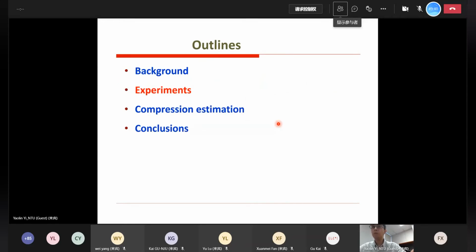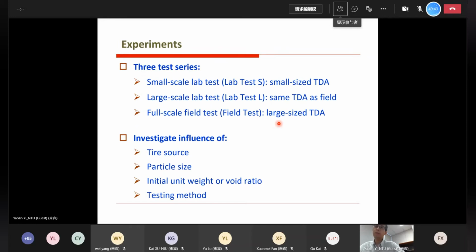Now I'm going to introduce the experiments. We did three types of compression tests. One is a small-scale laboratory test, relatively small scale, using small-sized TDA. Second, we also did a large-scale laboratory test. We used the same TDA as we used in the field. And the third one is a full-scale field test, using very large-sized TDA. We want to compare the results from the three types of tests and see if there is something in common, and whether it's possible to use a relatively small-scale test to predict the compression at the large scale. So that's the objective of this research.